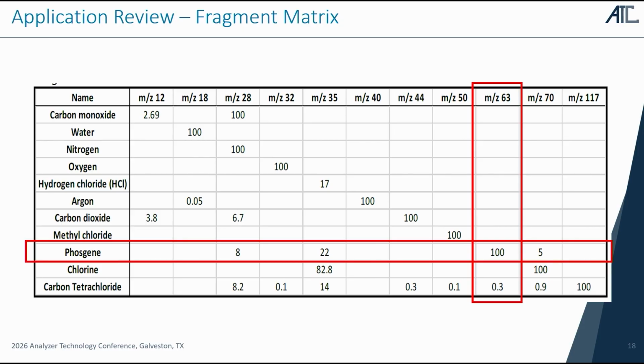So here we see Phosgene highlighted in red. We're measuring it at mass 63. And in this matrix, we not only are looking at air components, but we have additional contaminants that may interfere with the analysis of Phosgene that need to be taken into consideration. Particularly of interest for this, it would be carbon tetrachloride at a very low 0.3 ratio of intensity, but we have a very clear Phosgene peak at mass 63 for that analysis.